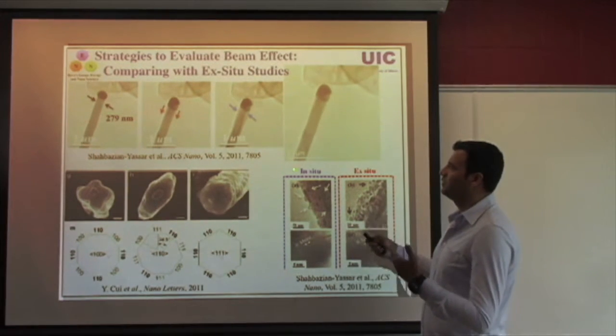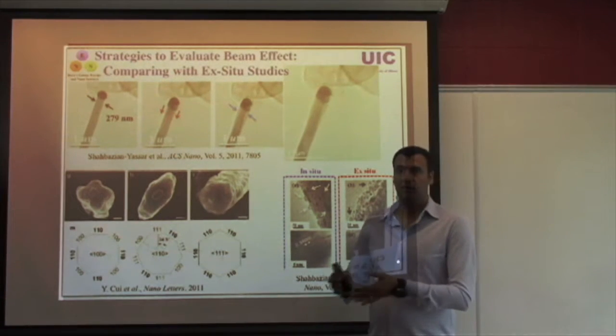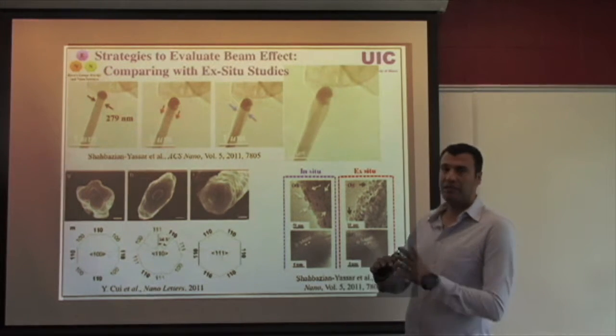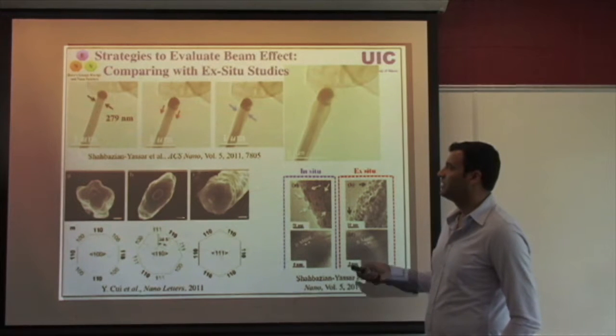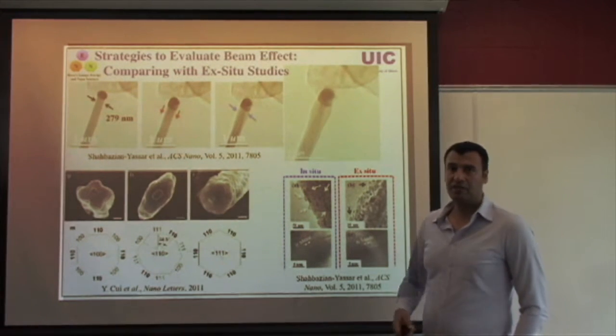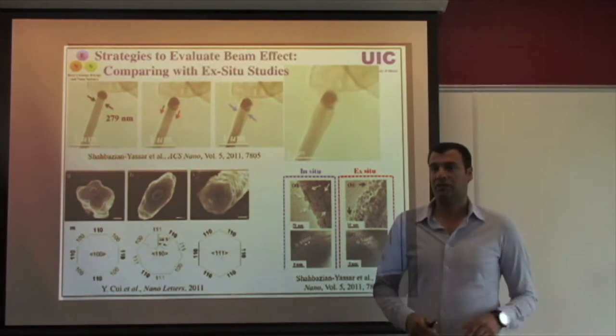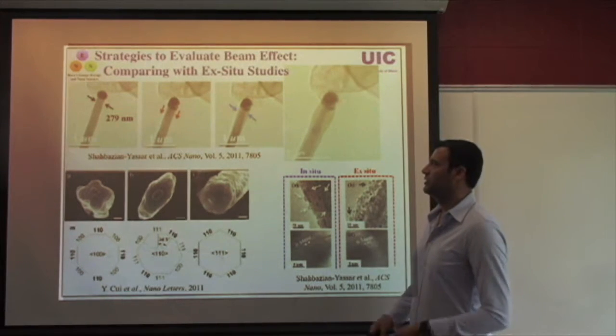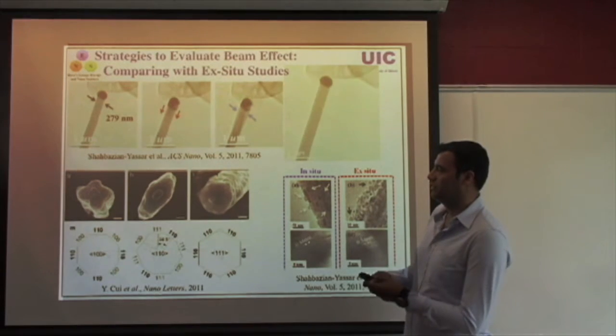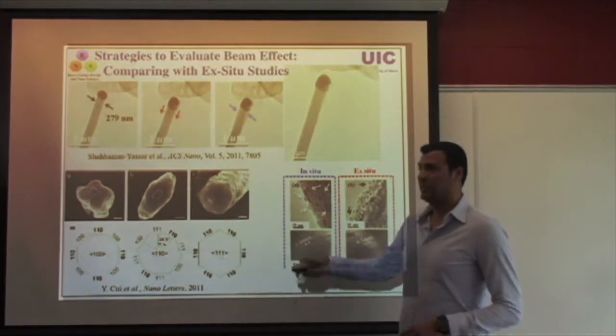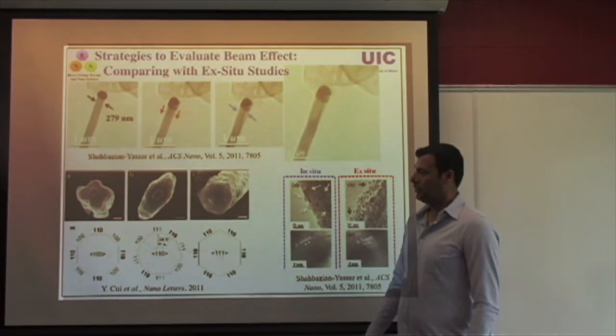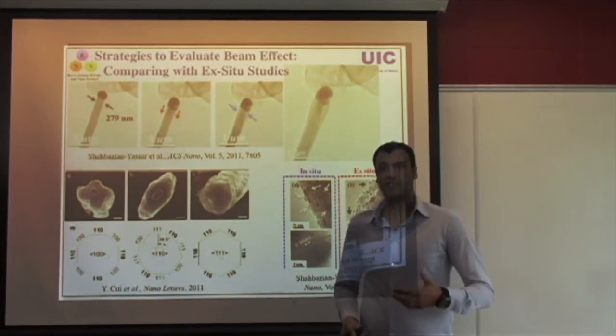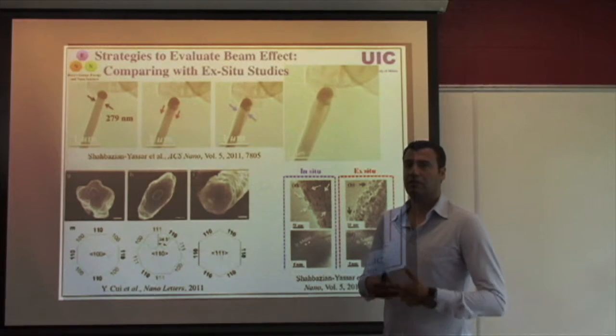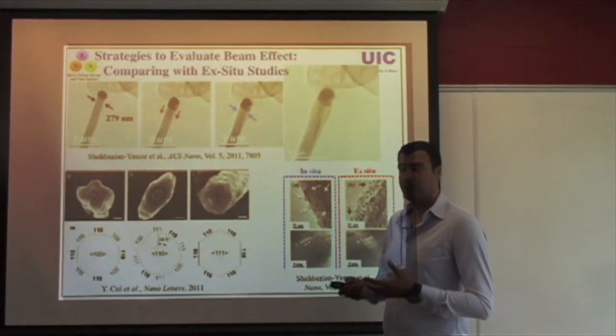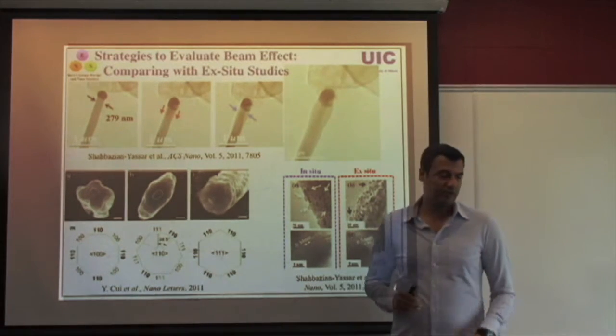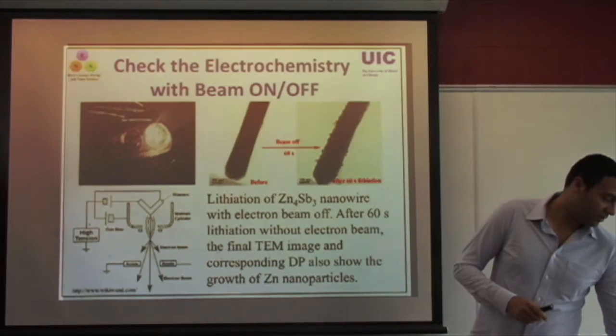For many years that we have been doing our electrochemical research, we have been working with groups that are mostly looking at battery applications and larger scale applications. And in many cases we see nice correlation between what has been done through electrochemical battery systems and in situ electrochemistry research. This is an example of the anisotropic growth of lithiation of silicon, which has also been observed by ex situ tests. So there is a nice correlation between the two, and this is in fact advice: if you try to report interesting in situ TEM results associated with electrochemistry, it would be good to do some ex situ tests and see if the behavior we are observing has a direct correlation.